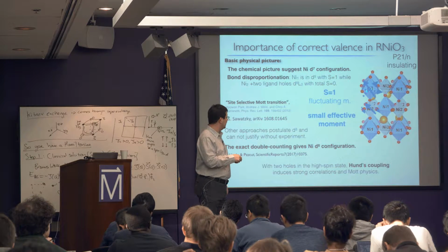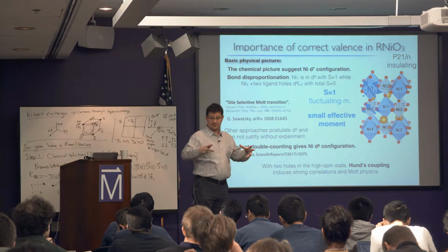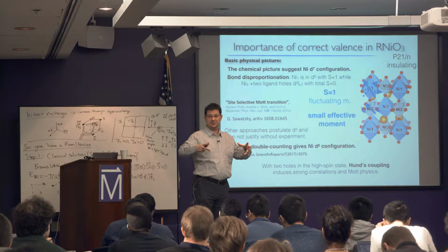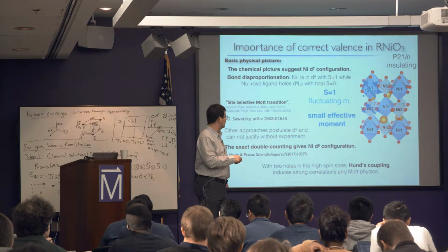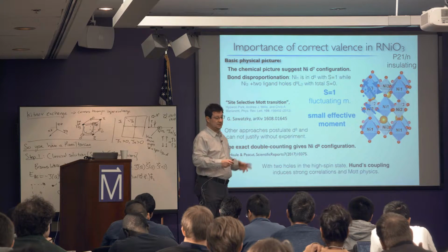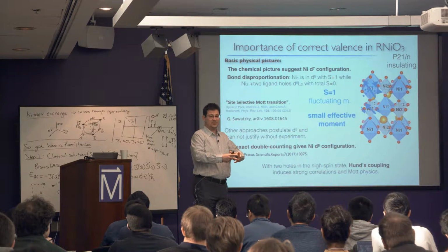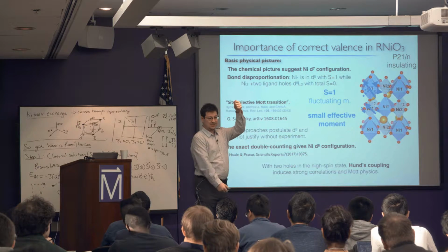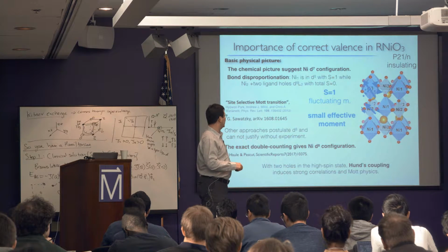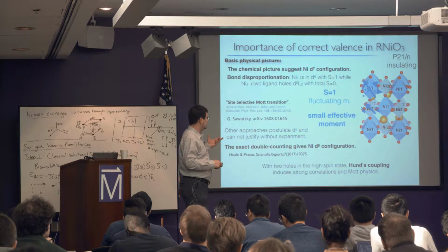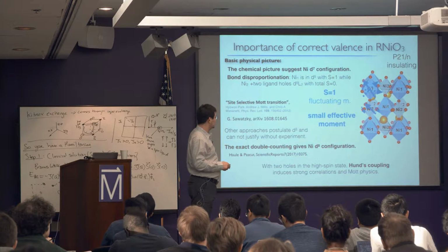So this nickel 1, in which there is expanded octahedra, of course, has very small hybridization with oxygen, and therefore it's Mott insulating, has high spin. But nickel 2, which is very compressed, then basically you have bonding, antibonding splitting of nickel states. They split, and you have a band gap. Now, this, of course, is hard to guess. There was a big discussion for a long time.